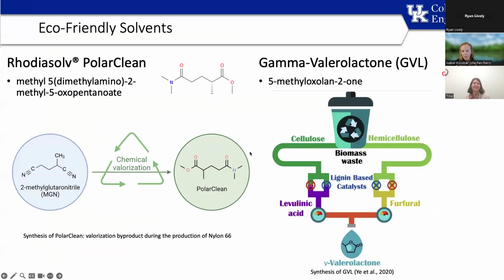So through the initial screening, we screened a heck of a lot of them, and we found that Polar Clean and GVL were the ones that had the potential to dissolve polysulfone, which obviously we went with polysulfone. That's one of the workhorses in the membrane world. It's an incredibly cheap, powerful polymer. We all love polysulfone. And from an academic standpoint, there are so many publications with polysulfone, we can always validate our work. So we like Polar Clean a lot because it's a chemical valorization.